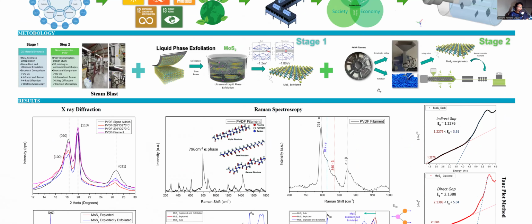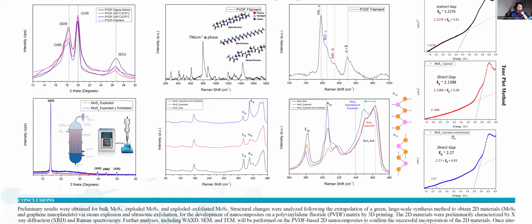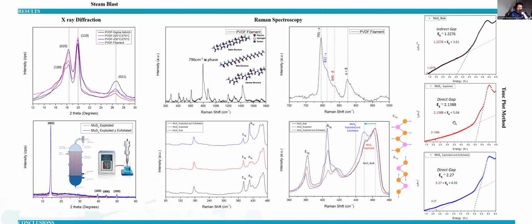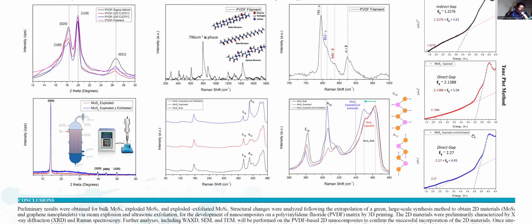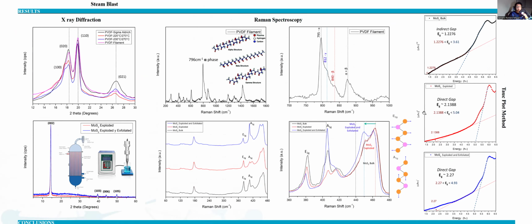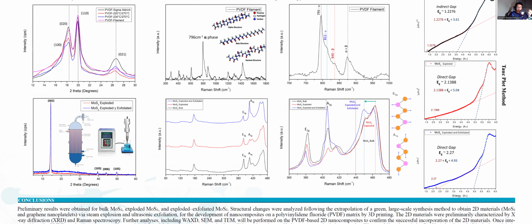We can assume, because of different investigations, that bulk material has, as we see, 1.2 electron volts, and in different layers, in this case monolayers, but in our case, the material that we have already synthesized or prepared has a different, increased band gap. So combining PVDF with semiconductor-grade molybdenum disulfide opens the door to flexible, high-performance piezoelectric nanocomposites by preparing and characterizing the base materials in this way.